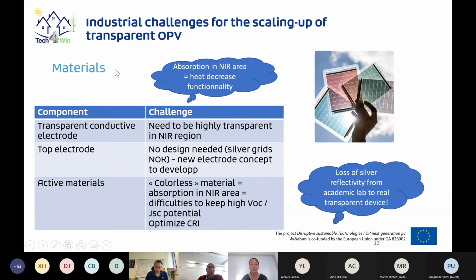If we go to the materials challenges for the transparency, one of them is the use of the transparent conductive electrode. Today, we are mostly using in the industrial scale a stack of ITO, silver, ITO, so IMI, which absorbs in the near-infrared region above 800 nanometers. There is a slight absorption. So when we use transparent OPV materials, polymers, we lose some of their absorptions in this area due to the transparent bottom electrode. So this impacts the JSC and the power conversion efficiency, and the impact can be between 5 and 10%.